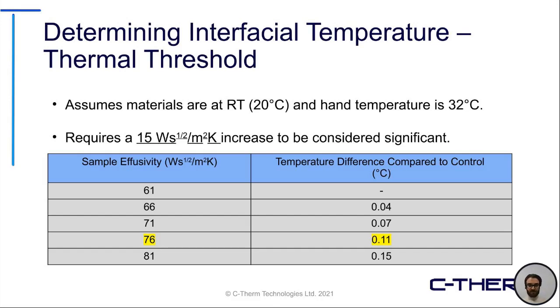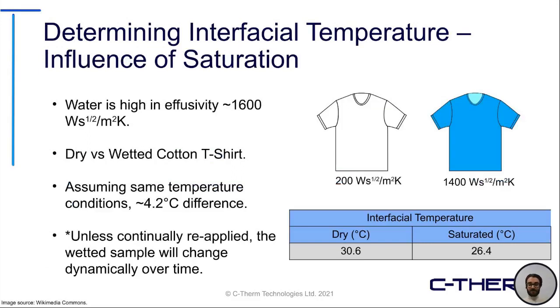Now, if you run through this thought practice and equation on your own, you will notice that the temperature difference between the skin and the sample will influence the overall difference in temperature that is experienced, but also the range of effusivities that you're comparing. For lower effusivity materials below 100, compared to the 100 to 200 range or the 200 to 300 range, the level at which the differences become significant does vary, and you will need different differences between that control and baseline sample and the new treated material to get the same level of difference in temperature that is felt. But you can use this to go through some different experimental studies.